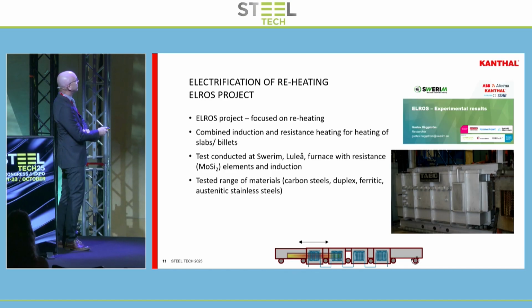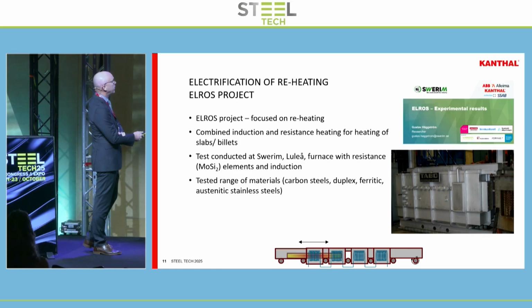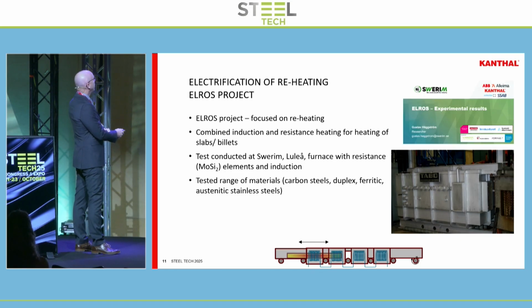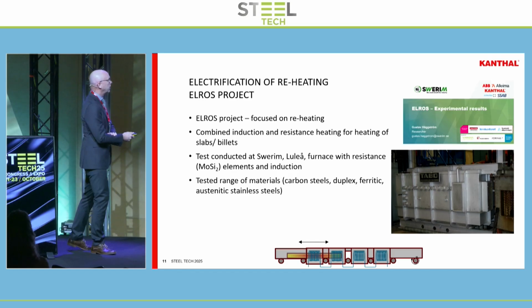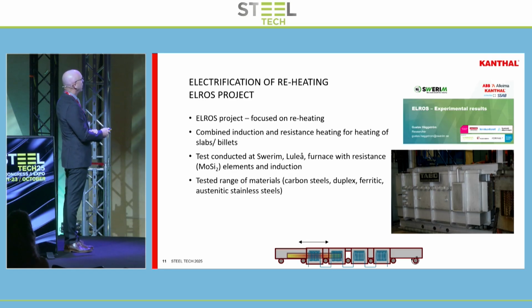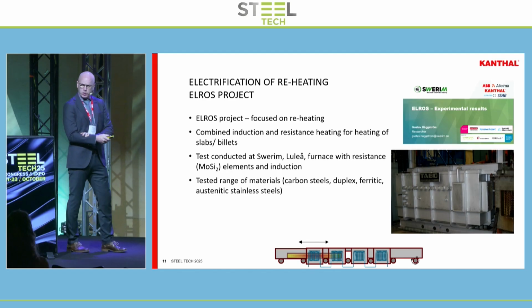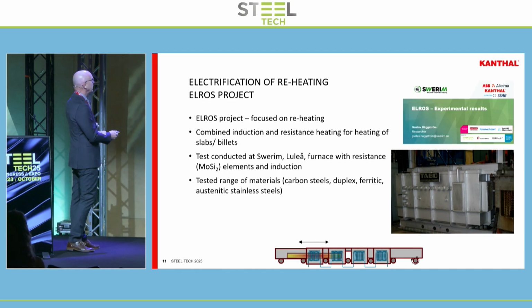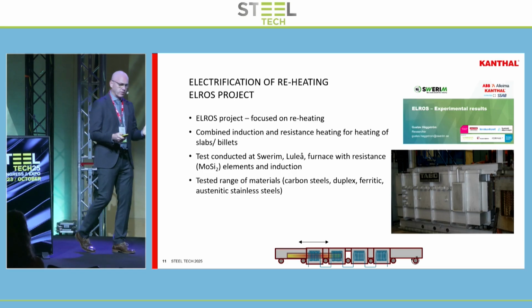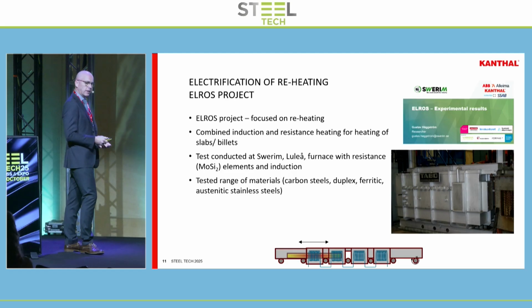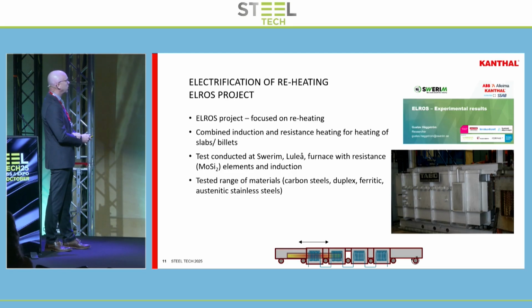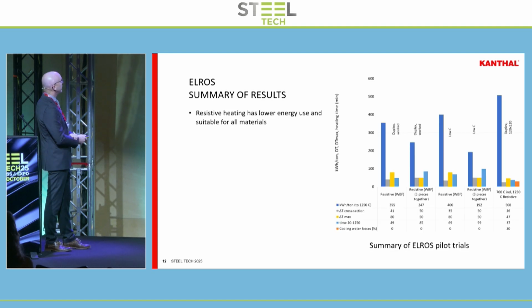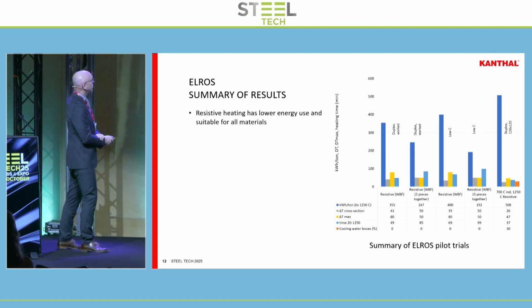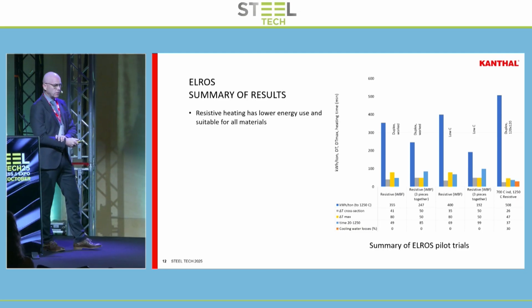But before that, as mentioned, this was a project that was done in Sweden, sponsored by Vinnova, with some other steel end users, SSAB, for example. It's called the Ellros project. It focused on combining resistance heating with induction heating. An interesting project. The tests were done in Swerim, Luleå in northern Sweden, where we combined induction heating with the resistance heating. And we tested a wide range of materials, from carbon steels up to austenitic stainless steels, to see how they work. I won't go into too much detail, but some salient conclusions are that resistive heating has a lower energy use and it's suitable for a wide range of materials. That can be established.